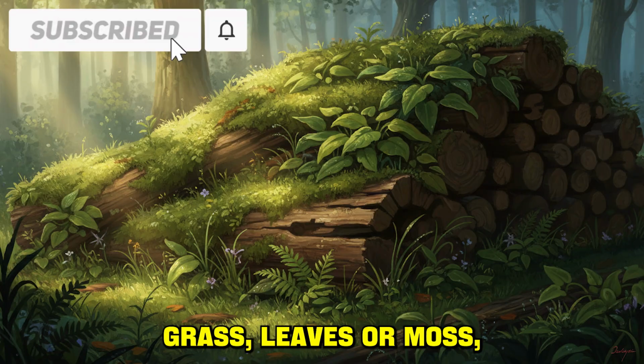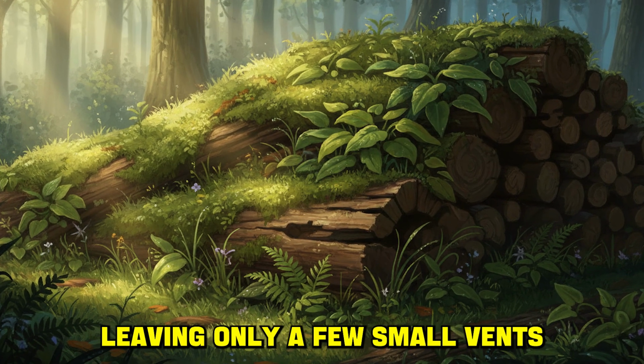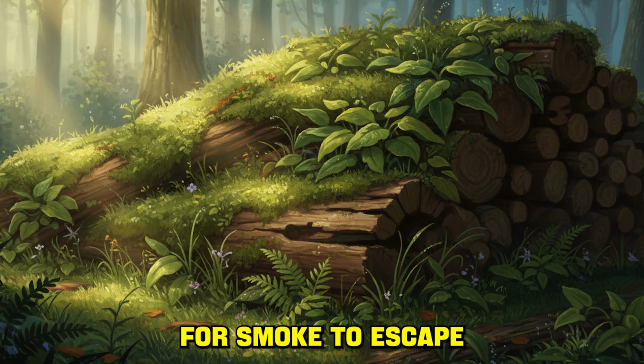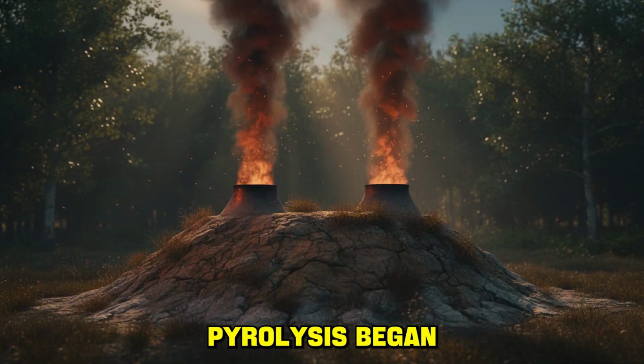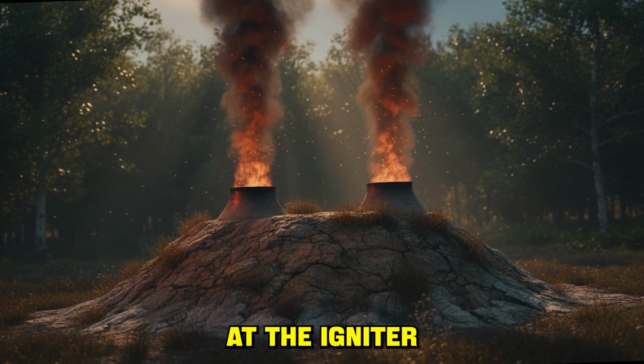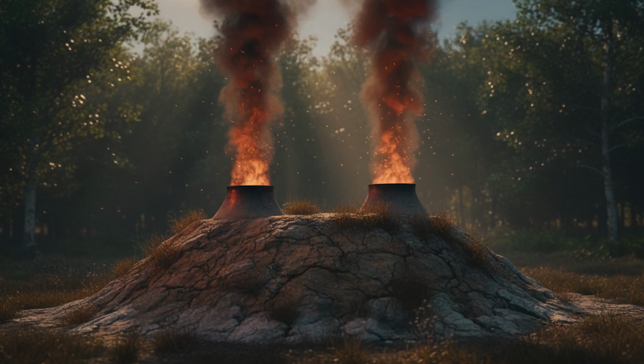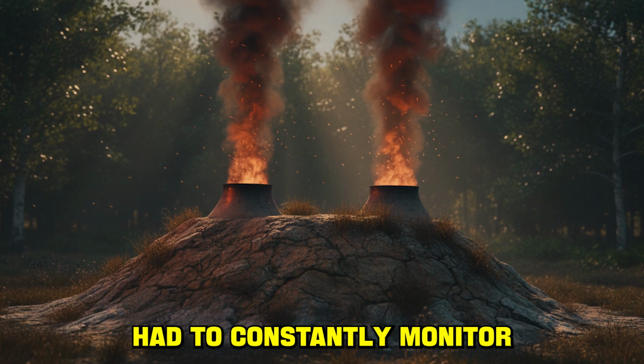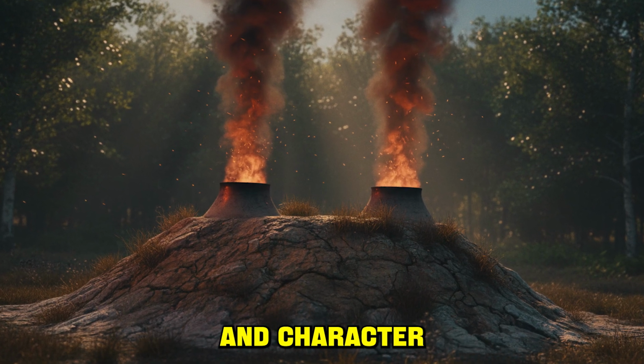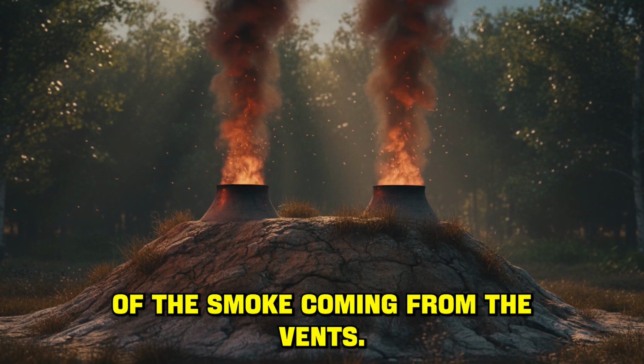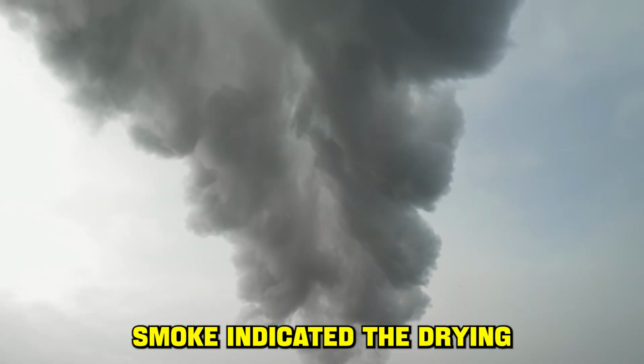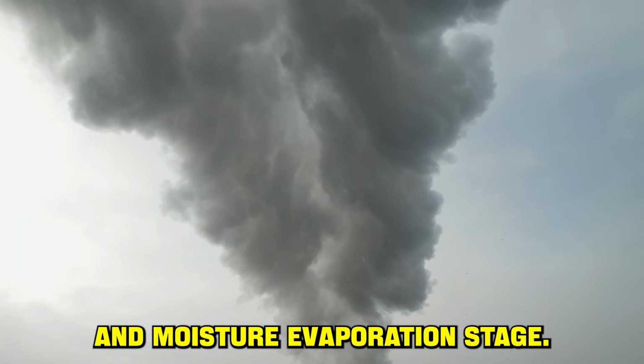The stacked wood was covered with a layer of damp grass, leaves, or moss, and then covered with earth, leaving only a few small vents for smoke to escape and control the process. Pyrolysis began at the igniter and slowly spread throughout the pit. The charcoal burner had to constantly monitor the color and character of the smoke coming from the vents. Thick white smoke indicated the drying and moisture evaporation stage.